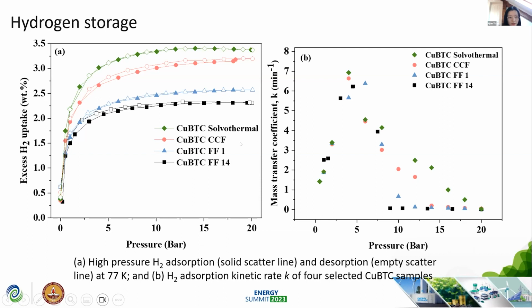As you can see from these two figures, the copper BTC with the largest crystal size exhibits comparable hydrogen uptake to the copper BTC from thermal synthesis, and it's higher than the copper BTC with smaller crystal size. This result is also the same as the hydrogen absorption kinetic rates. In other words, the copper BTC with the largest crystal size shows a higher absorption rate than the copper BTC with smaller crystal size, which means this sample synthesized with reduced energy and reduced solvent can exhibit higher hydrogen storage, which has promising implications.